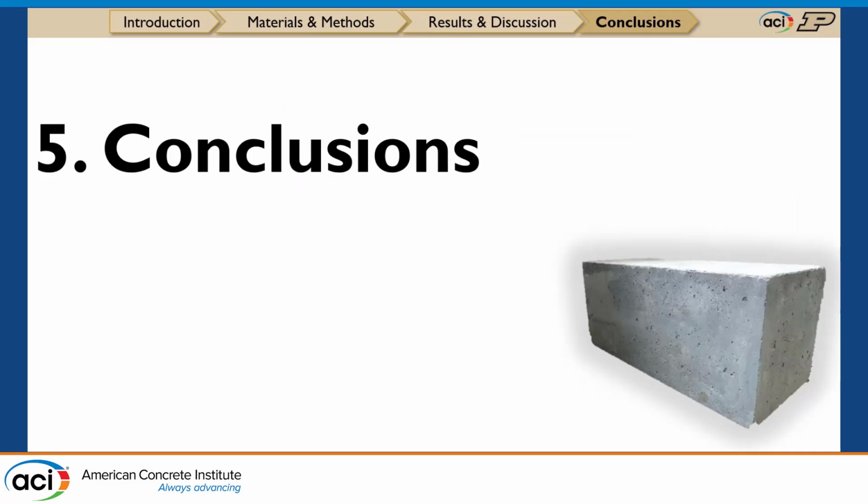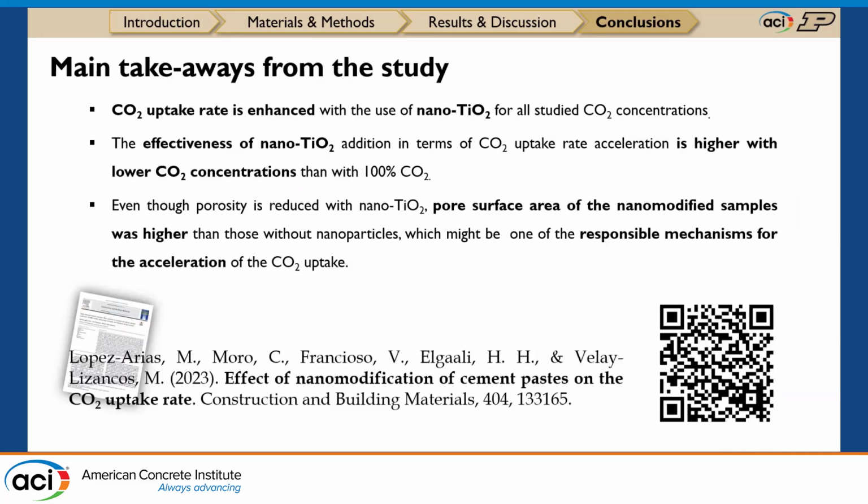So as some conclusions or takeaways from this study, we did see that CO2 uptake rate was enhanced when we use titanium dioxide nanoparticles for all CO2 concentrations. However, the effectiveness of our nanoparticles is higher when you're exposing it to lower CO2 concentrations. And we think that one of the reasons this may happen is because of the increase of the pore surface area when you're adding these nanoparticles.